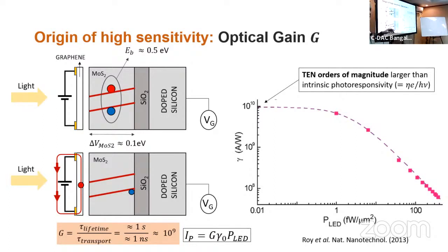Typical silicon-based photodetectors have a responsivity of 10 to the power 1, about 1 ampere per watt, current in amperes per power in watts. Whereas these kinds of detectors can now achieve 10 to the power 10 amperes per watt, which is, as I said, about 10 orders of magnitude higher. So it was essentially a completely different type of detection.